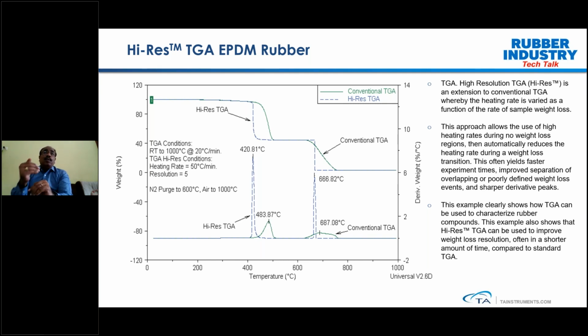So in this case, though we started off the heating rate initially at 50 degrees centigrade per minute, as soon as the sample reaches the initial weight loss, which is observed around 420 degrees centigrade, the heating rate will be completely reduced, which allows the sample kinetics to complete, and we allow the sample to decompose totally, and that will give a sharper weight loss. Afterwards, once the weight gets stabilized, your derivative is coming close to zero, the heating rate kicks off again and goes to the higher range. Finally, we go to the next level of decomposition.